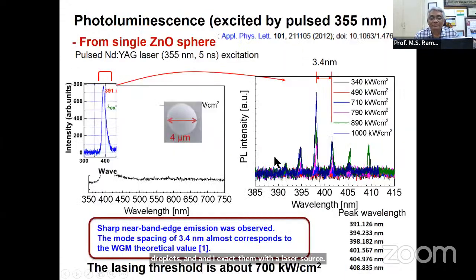What happens is, if you look at the normal photoluminescence emission from zinc oxide, you see a nice sharp peak at 391 nanometers.